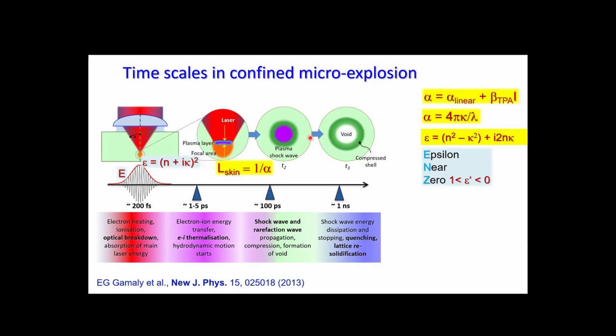The most interesting situation for energy deposition is when you have material which is called epsilon near zero. This is when the refractive index, real and imaginary part, begin to be very similar. When it is zero, this is the definition of dielectric breakdown. So you usually drive material towards dielectric breakdown, but with controlled energy deposition, because pulses are short, and you can basically know how much energy you deposit with the peak of your oscillating electrical field. You can tune material into different modifications.